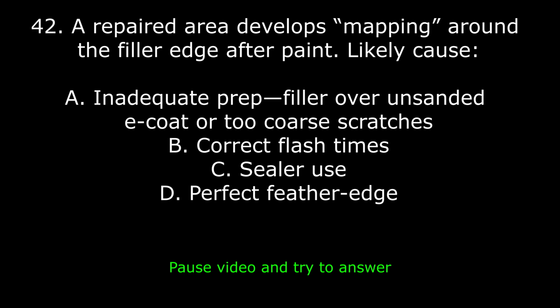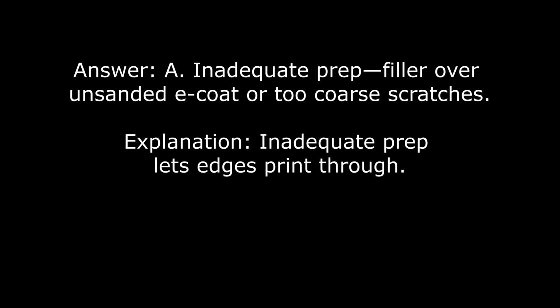42. A repaired area develops mapping around the filler edge after paint. Likely cause: A. Inadequate prep, filler over unsanded E-coat or too coarse scratches. B. Correct flash times. C. Sealer use. Or D. Perfect feather edge. Answer A. Inadequate prep, filler over unsanded E-coat or too coarse scratches. Explanation: inadequate prep lets edges print through.